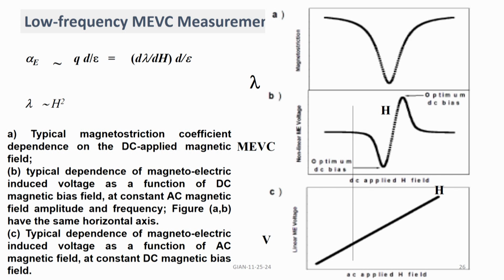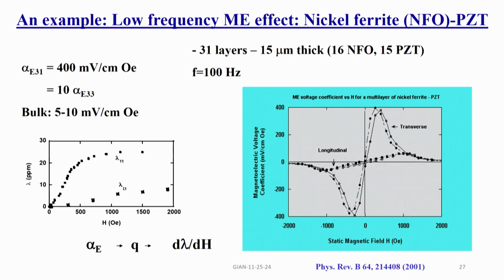Then the bottom one is what you would measure if you change the amplitude of the AC magnetic field. If you do that, it's a linear function, and the voltage will increase linearly with the applied AC magnetic field. If you take the slope of this, that is the voltage coefficient times the thickness T. You take the slope, divide by the thickness of the composite or the PZT, then you have the voltage coefficient. So that's what is shown in this particular example.